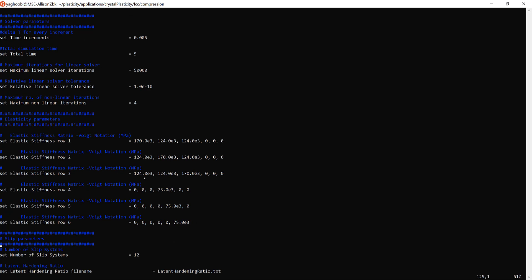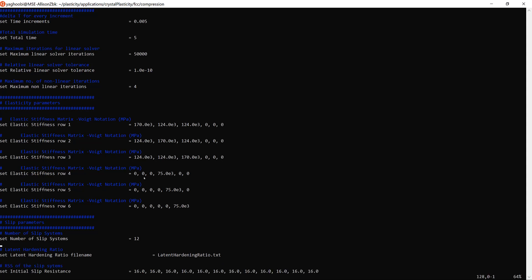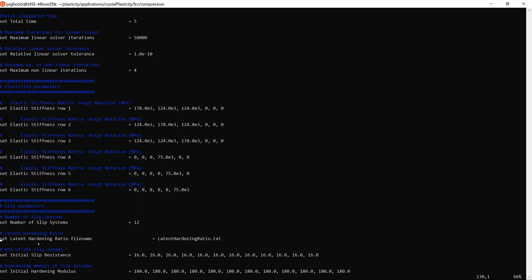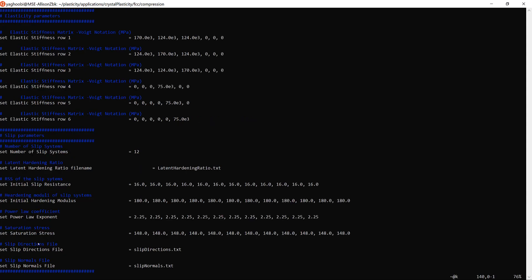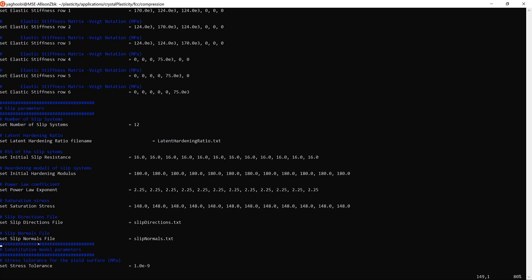The next six lines are the elastic modulus of the system — it's a 6x6 matrix defined here in megapascals, though you just need to maintain unit consistency. The next line is 'number of slip systems' — for an FCC system this is 12. 'Set latent hardening ratio file name' points to the latent hardening ratios matrix file. The next four lines introduce the crystal plasticity model parameters: initial slip resistance, hardening modulus, power law exponent, and saturation stress. The following two lines give the slip direction and slip normal file names.